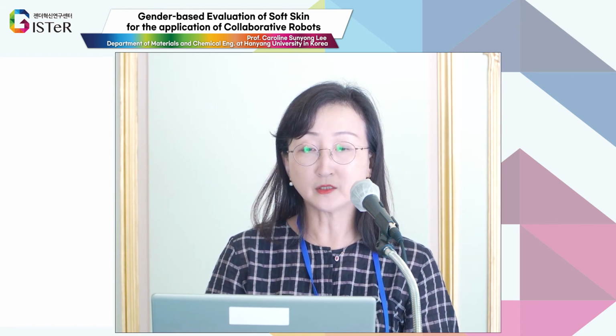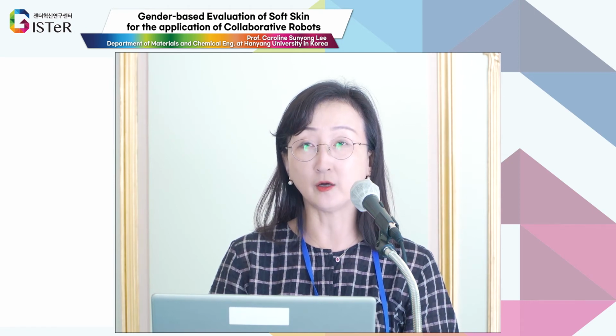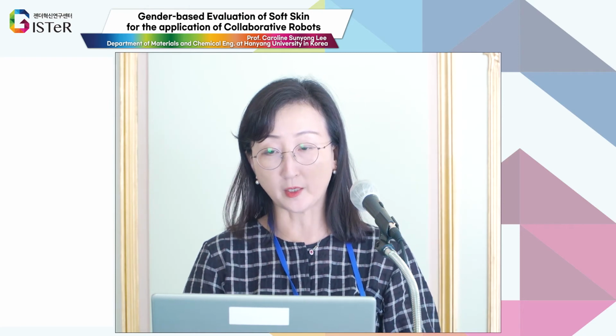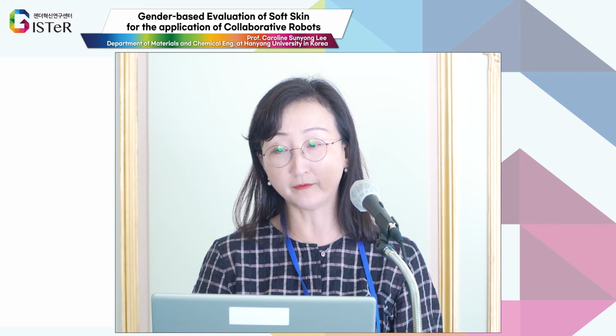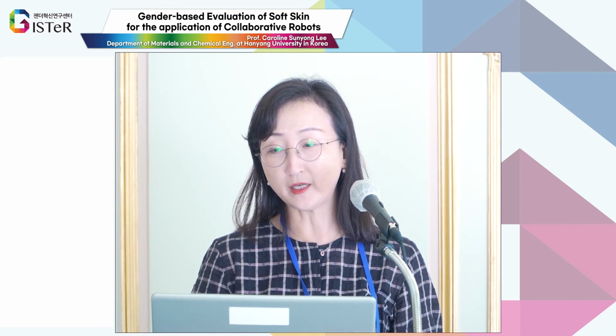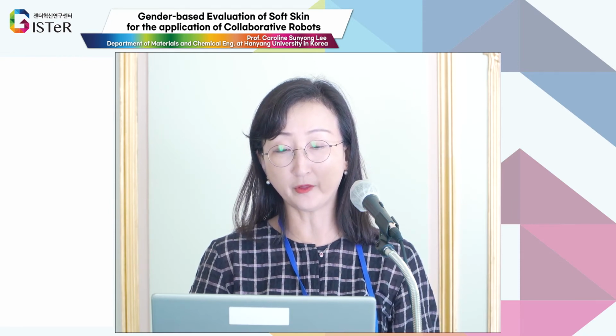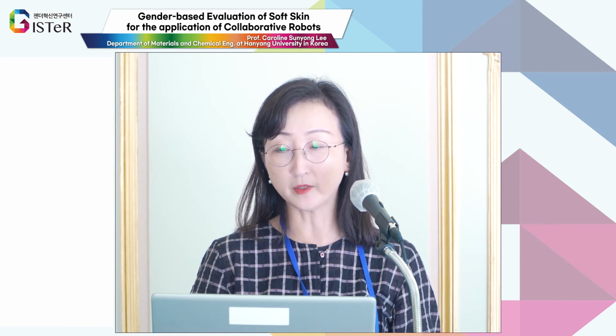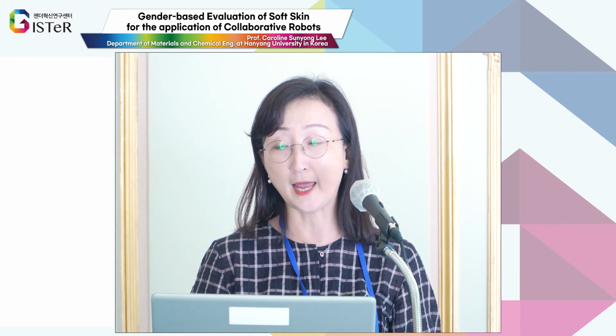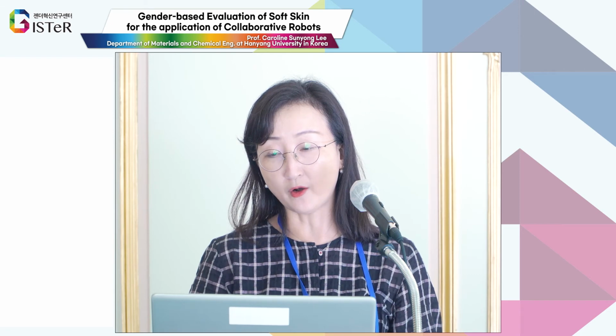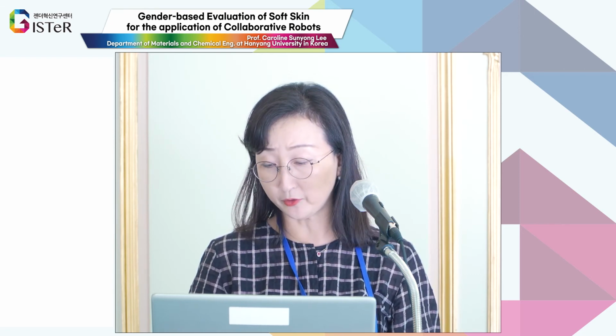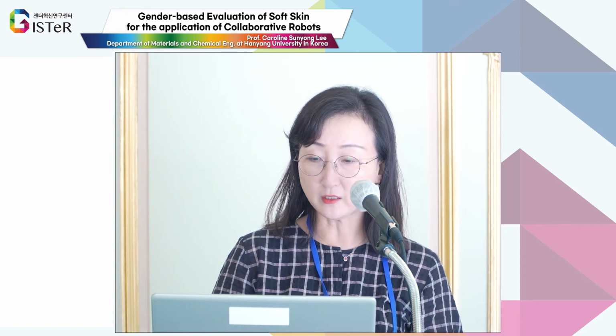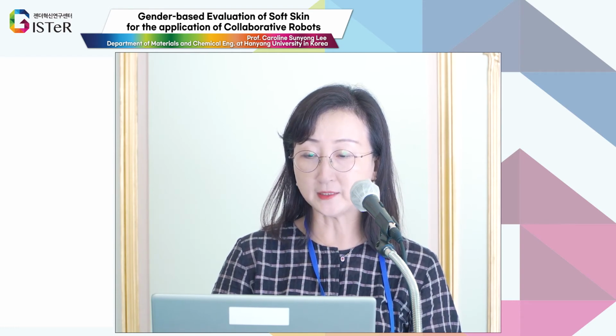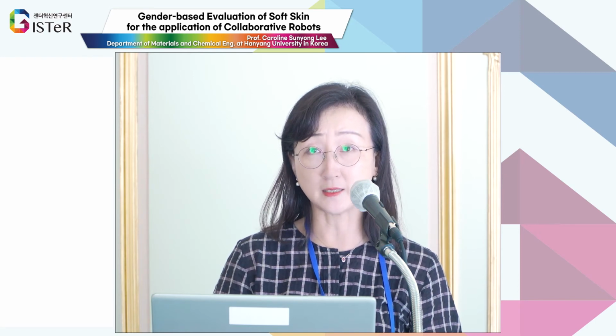Here are the results for the statistical analysis that we have done on the preference survey, and we have made an effort to consolidate the factors of age and gender to come up with one optimal soft robot skin material. The first one is regardless of age: we tried not to consider age, and then selected the preferred material for both male and female. Regardless of age, the PDMS sample was preferred by men for both shoulder and elbow contact, whereas the 10 millimeter PDMS and 10 millimeter Ecoflex were preferred for the shoulder and elbows for women, respectively. Finally, as I have said before, the factors of age and gender were consolidated to find the optimum skin material for the cobots. Based on the preference survey results, skin with combined PDMS and Ecoflex seems to be the favorable material for both men and women, regardless of age and contact body parts.